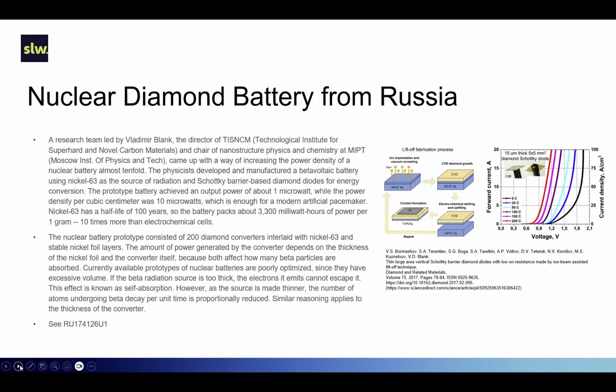Nickel-63 has a half-life of 100 years, so the battery packs about 3,300 milliwatt hours of energy per 1 gram, 10 times more than electrochemical cells. The nuclear battery prototype consisted of 200 diamond converters interlaid with nickel-63 and stable nickel foil layers. The amount of power generated by the converter depends upon the thickness of the nickel foil and the converter itself, because both affect how many beta particles are absorbed.